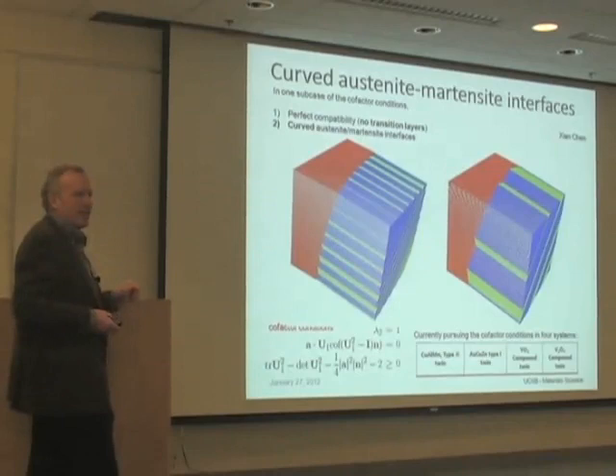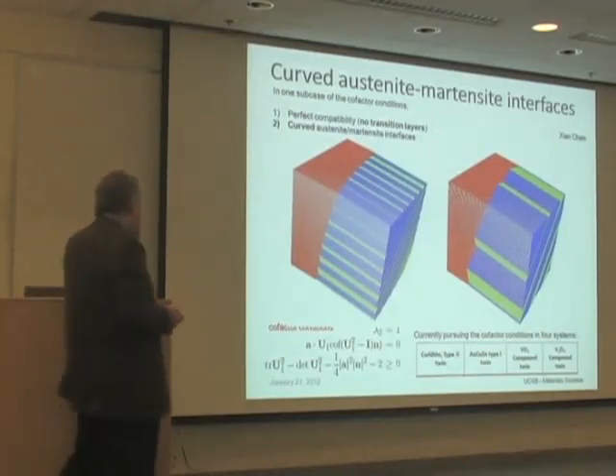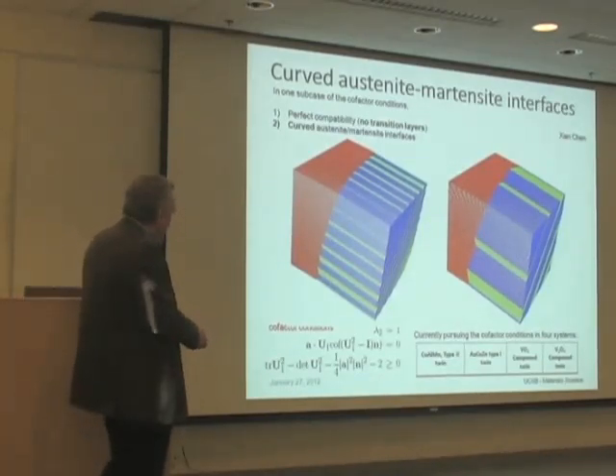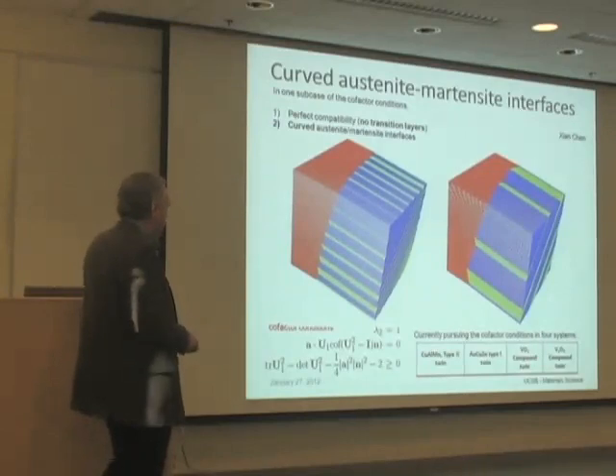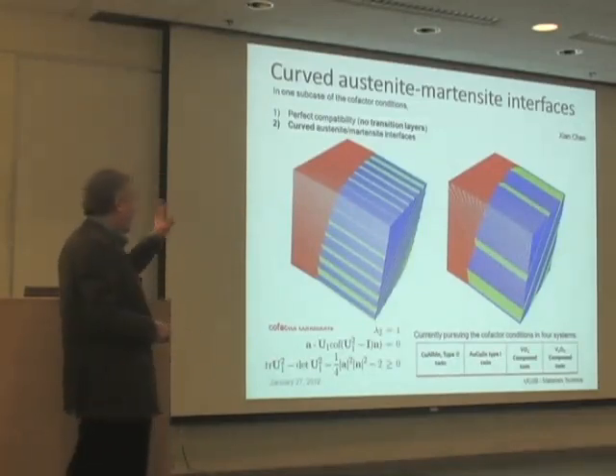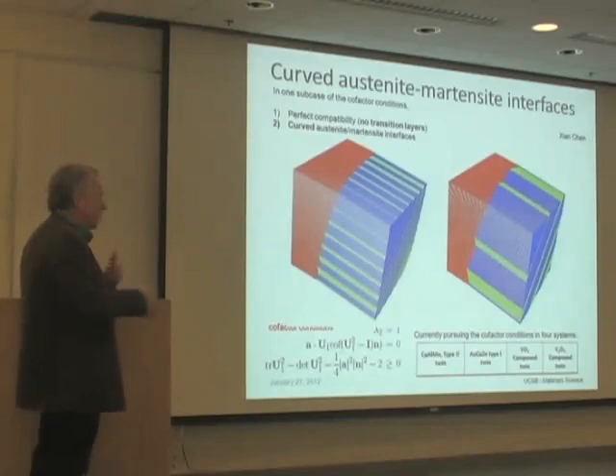We have actually four material systems that are very close to satisfying the cofactor conditions. VO2, we think it can be doped to satisfy those conditions, and even V2O3. And copper, aluminum, manganese, type 2 twins, and gold, copper, zinc, type 1 twins. This is probably the one we're closest to now. So we hope to demonstrate this, and we think this could have a tremendous reversibility in phase transformations.